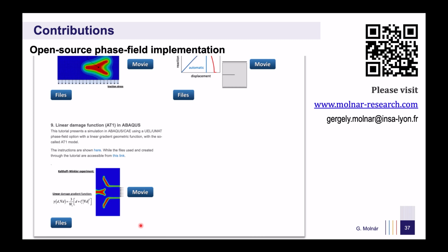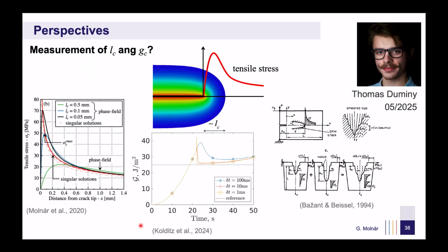However, there is still much work to be done. For instance, it would be valuable to observe how the process zone develops in real experiments. In the near future, Thomas' work will focus on developing non-singular fits for phase field models. It is well known that the traditional singular Williams series approach overestimates the toughness in simulations. To address this, our approach aims to incorporate a regularization field analytically, providing a more accurate and physically consistent representation.